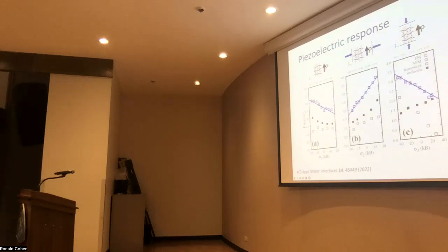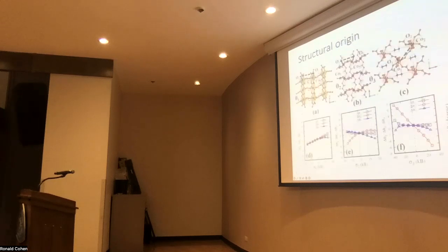In this case, we can once again take a look at the decomposition into the response of the framework and the response of the molecule. And actually for the transverse direction, it's quite the opposite. The framework almost doesn't play any role. It's entirely due to the contribution of the molecule that we observe the different sign of the piezoelectric slope.